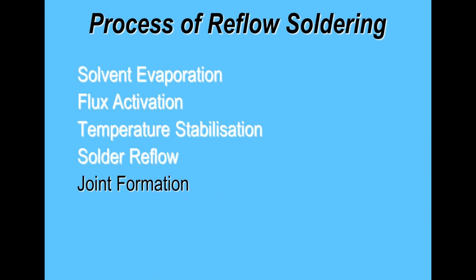Now, solder paste can reflow, but you don't necessarily get a joint forming until we've overcome wettability issues with the components or PCBs. So we can have solder in a liquid state, but it may not form a joint or a true intermetallic formation. And this may be to do with solderability. It may be to do with the termination not actually sitting in the solder paste anymore. It's actually held above the surface. So reflow of solder paste and joint formation really should be dealt with separately.